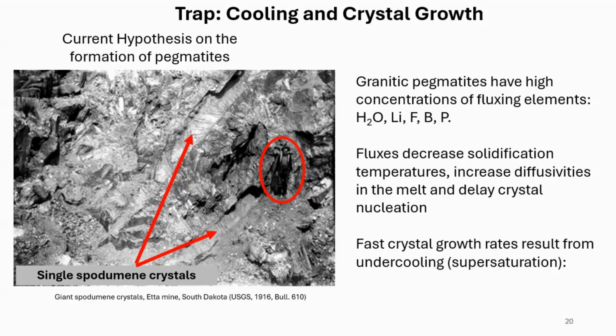So what happens is when you have water as a flux, you may only have to have a 20-degree supercooling to crystallize. Where when you add the fluorine and the lithium, it becomes greater. You need a larger decrease in temperature in order to nucleate crystals. So the fluxes increase diffusivities, but they also increase metastability. You have to have a larger supersaturation in order to crystallize it. So as a result of that, we end up with actually fast crystal growth rates as a result of supersaturation, as a result of undercooling. And that's why we believe that there are these large crystals.